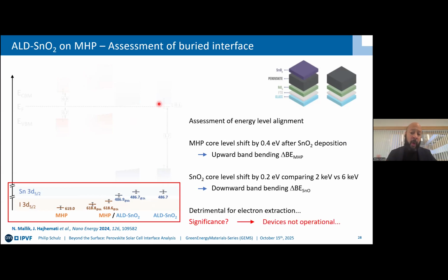What we saw is that devices were not operational, and we were able to remedy this to some extent by introducing a thin PCBM buffer layer, but power conversion efficiencies were not very promising, and thus we did not further pursue this with the ultra-thin PCBM layer. But note that we still use tin oxide in our devices and modules here at IPVF if properly buffered.